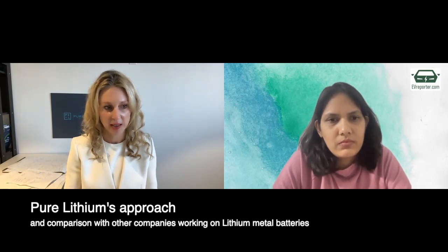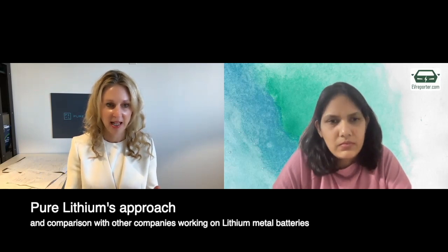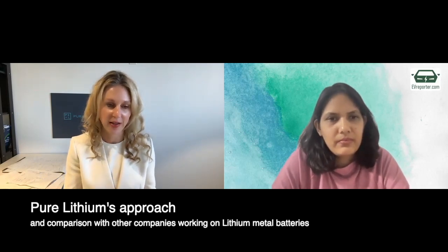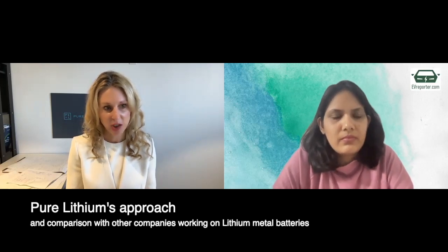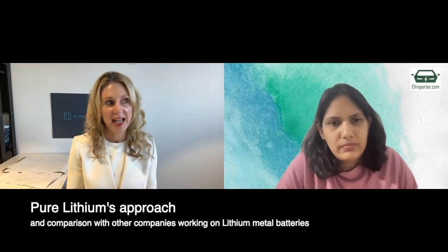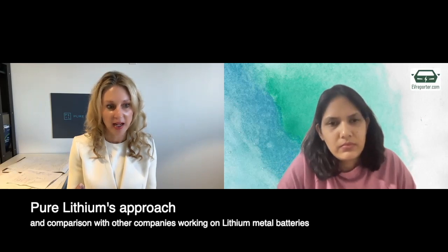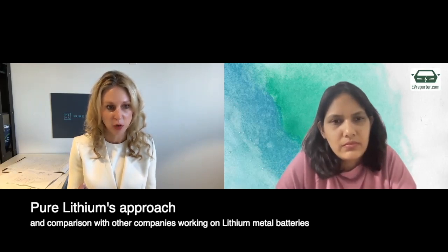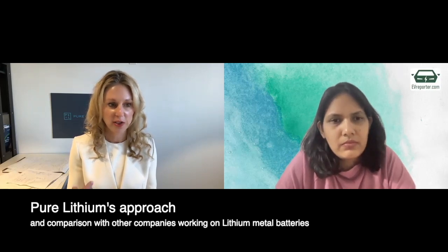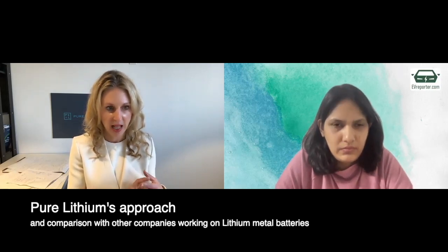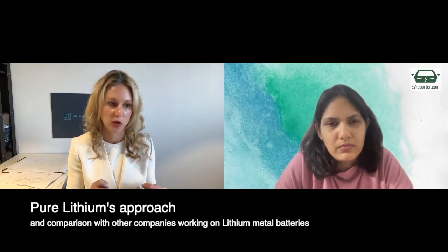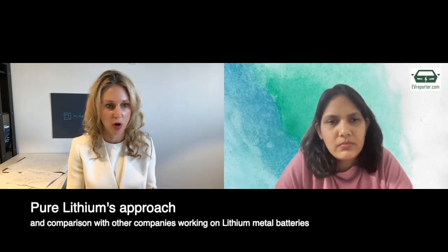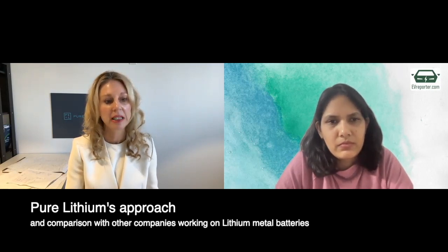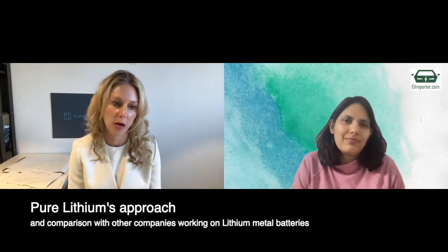What QuantumScape does is they take the lithium out of the cathode and then they deposit it onto the anode, very similarly to the lithium ion battery. It takes a substantial amount of time, and you can't delithiate these cathodes all the way. They need to have lithium in them or the structure will collapse. So they're using the most expensive form of lithium, and it's much more difficult to actually form a lithium metal electrode that way. So we could not be farther apart from QuantumScape.